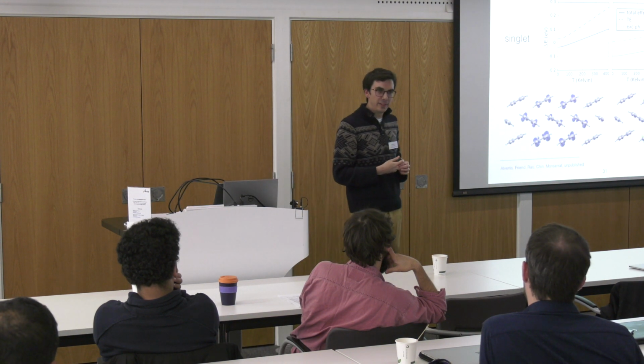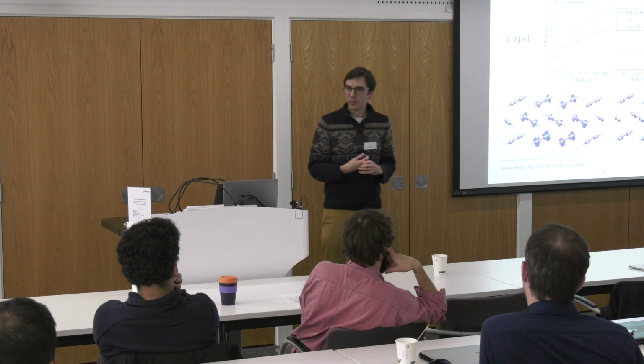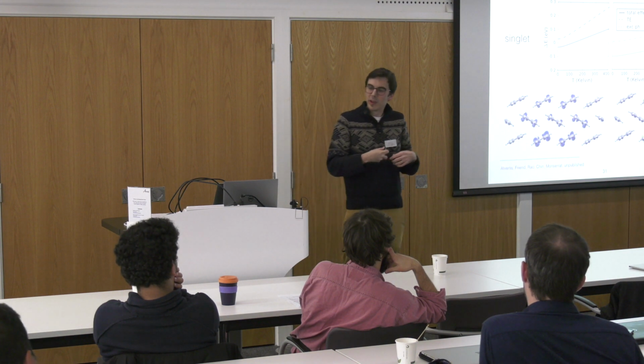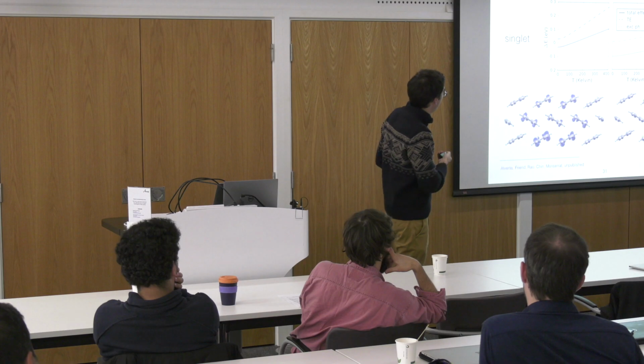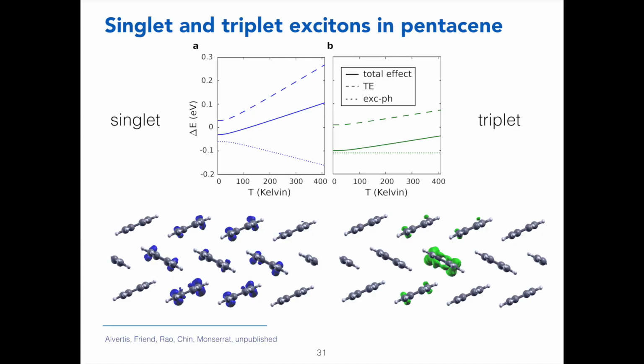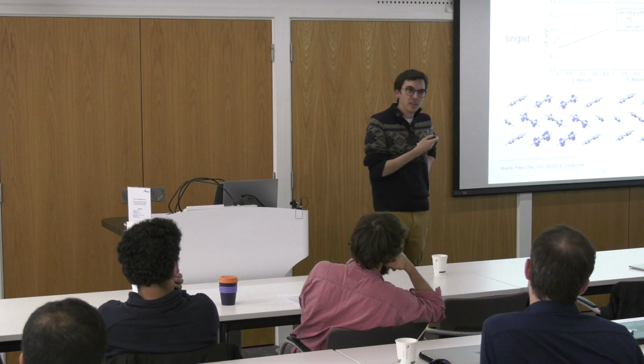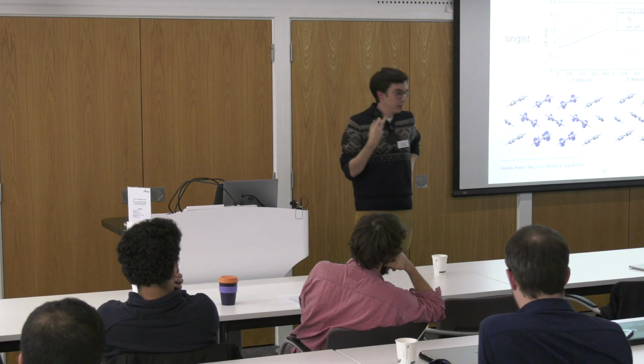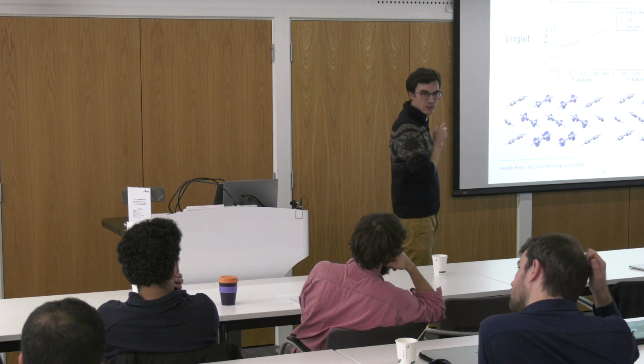And what we find is that this has enormous consequences for the coupling of these excitons to the phonons in the system, which one way of measuring is looking at the temperature dependence of these excitons, and that's what's being plotted here at the top. So let me start with the singlet exciton. What we have here is this dotted line, which is the temperature dependence of the exciton energy level arising from exciton-phonon coupling. Then we have that dashed line, which corresponds to the temperature dependence of the exciton arising from thermal expansion. And then we have the solid line, which is the combination of both.